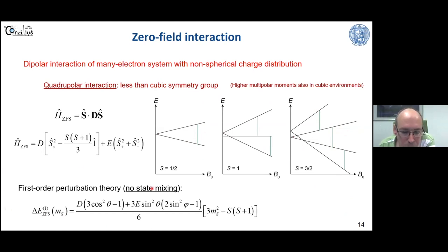If you just take first order perturbation theory, then this is the equation with which you can calculate the energy shift due to the zero field splitting, and you have the D and E parameters here. You find those here again. Then you have the angular component. You see here the 3 cosine squared theta minus 1 term again. And if you forget about this E term for now, then you get paired patterns in your spectrum. And here you see that the shift is proportional to M_S squared. That means you always get equal shifts of M_S states with the same magnitude but different sign. For example, the M_S minus and plus 1/2 states will be shifted by the same value, and the M_S plus and minus 3/2 states will be shifted by the same value. And so you always get these doublets which are shifted with respect to each other, and those are called Kramers doublets.